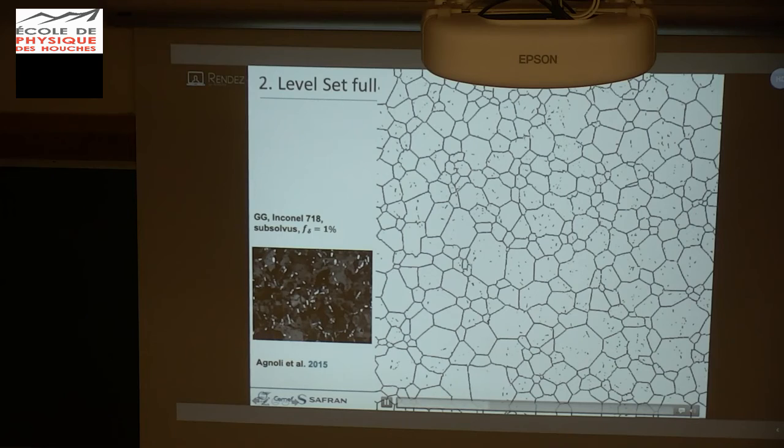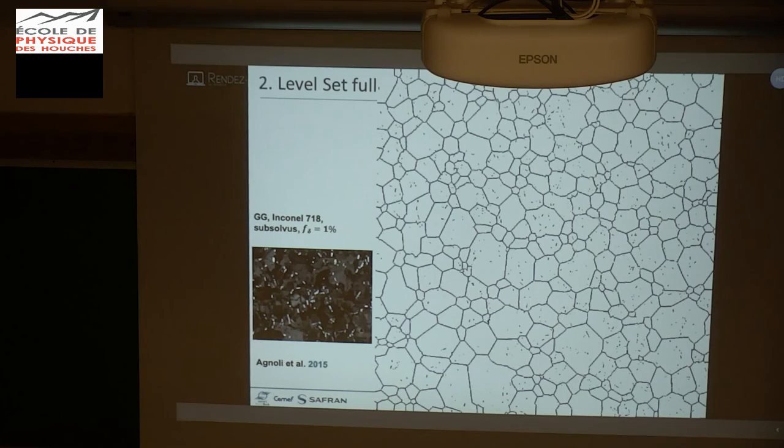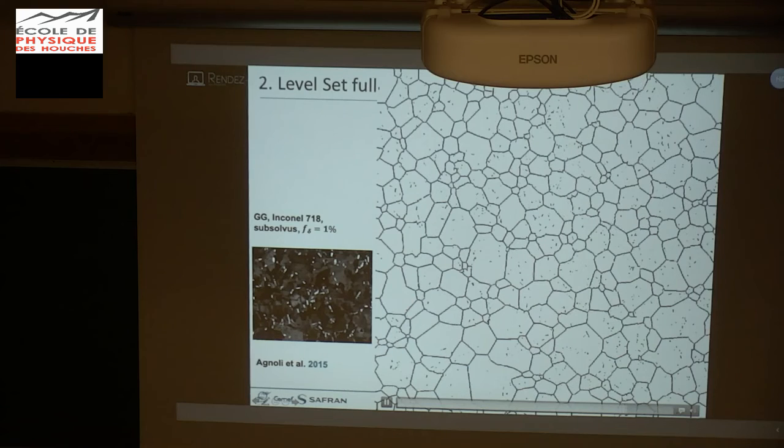And we can, for example with level set simulation, test whether it is important to take into account the wedge shape of the second phase particles, or whether we can approximate them by circular objects. We can compare this kind of simulation with the real shape against the same simulation where we describe the second phase particles as circles, and see if the approximation has an impact on the prediction. And it's exactly what I explained at the beginning: this kind of simulation is interesting not only to predict the microstructure, but also to discuss at the polycrystalline scale some hypotheses of the mean field numerical simulation, such as whether it is important to take into account the real morphology of second phase particles or not.